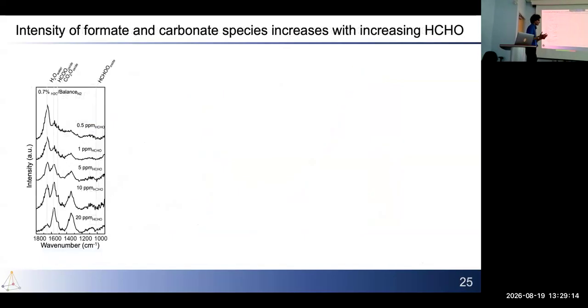So as usual, we have a result, we are excited, we want to see what's going on the surface. So we turn again to in situ IR in this case, and then see what are the reaction intermediates as you increase the concentration from 0.5 ppm all the way to 20 ppm.